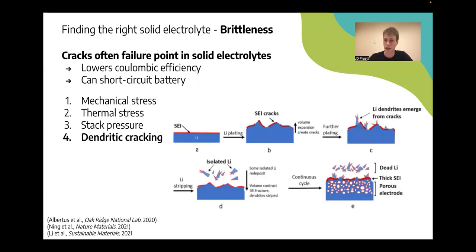Maddie covered this a little bit in his lecture, but I'll just expand on it a bit. So there we see a lithium anode and SEI, that's what I mentioned, solid electrolyte interface. And effectively what happens is as we start running this battery and lithium gets redeposited on that anode, it's not going to perfectly redeposit in some sort of perfect flat plane to reconstitute that initial nice rectangular shape of lithium. It's going to redeposit kind of in odd places, causing those places to grow unevenly. As we get that volume expansion, it's going to cause cracks in that solid electrolyte interface. As that plating process continues, we start to get lithium dendrites.